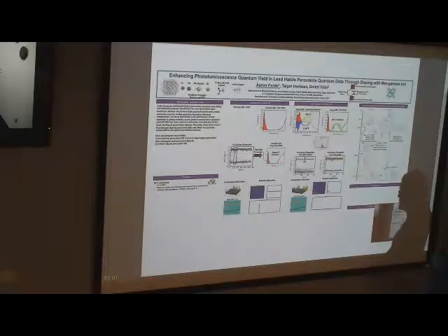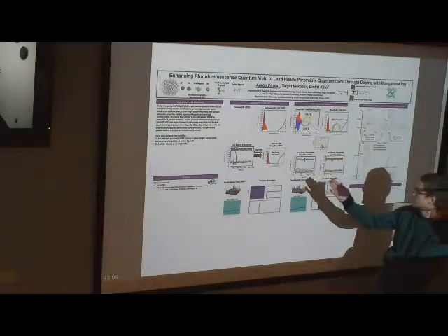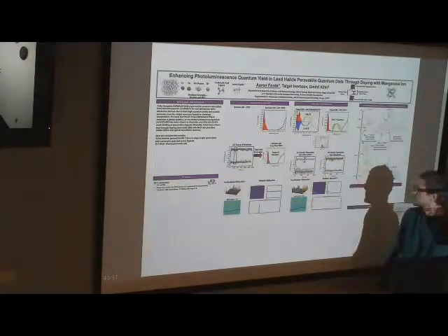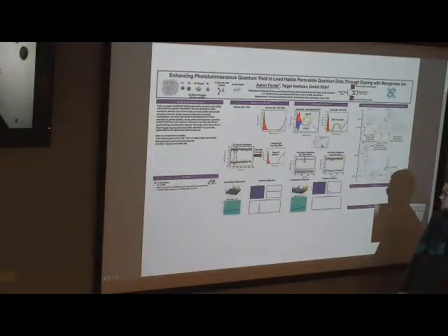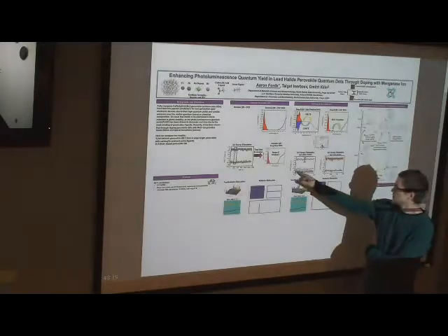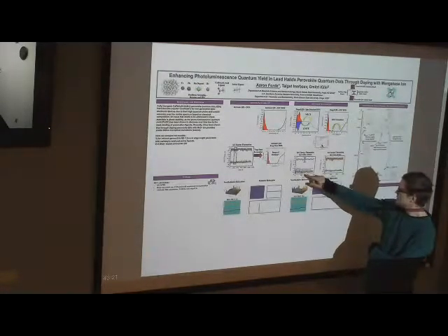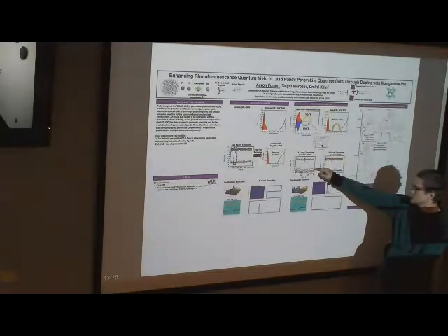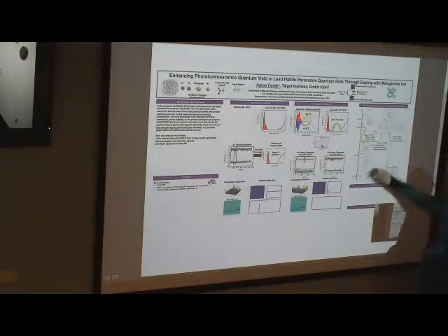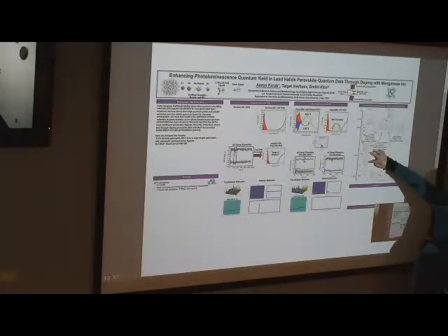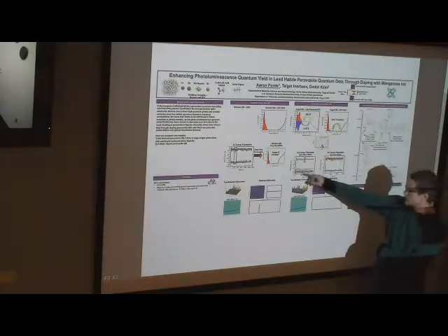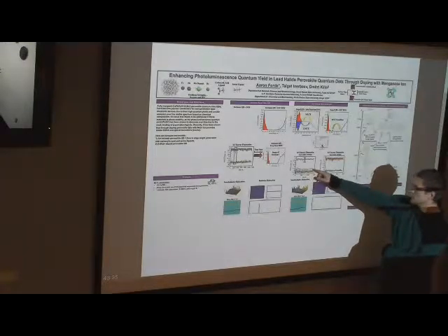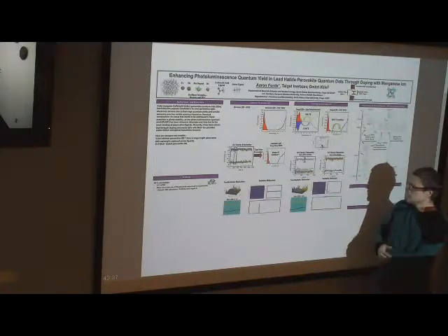And what we did is we tracked, same deal as with the intrinsic dot, how the energy states fluctuate in time along the molecular trajectory. And we can see that for the spin up cases, the two topmost energy bands correspond to these 2 states here within the gap. And you can see that the states don't change at all in time.